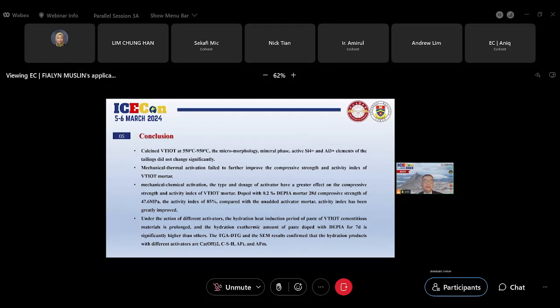5. Conclusion. Calcined VTIOT at 550 to 950 degrees, the macromorphology, mineral phase, active silicate, and aluminum element of the tile didn't change significantly. Mechanical thermal activation failed to further improve the compressive strength and activity index of VTIOT mortar. The mechanical chemical activation type and amount of activator have a greater effect on the compressive strength and the activity index of VTIOT mortar.